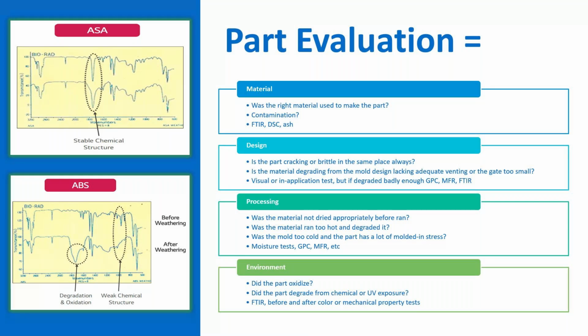So are you looking at a product that's already on the market or something similar? What material was being used? Is there contamination within the material? Was that particular lot of material a problem, if we're trying to figure out the issue? We could do FTIR to make sure the right material was being used. We could use DSC, same thing, to continue to make sure we're using the right material. Ash content testing, if it was filled. Was it supposed to be a 40% glass filled grade and it's testing at a 20? Those are things we can do to check that it's where it's supposed to be.